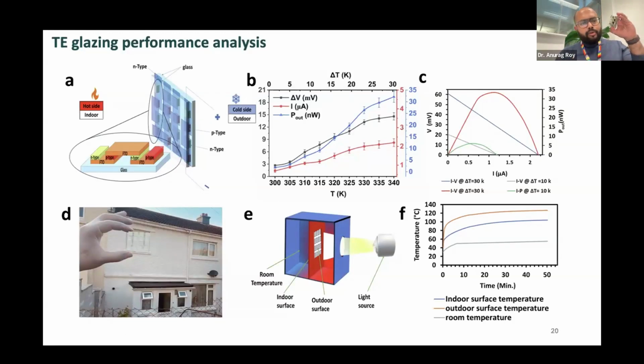So this is our thermoelectric nano generator. One single unit can produce 3 to 5 nanowatt. In this case, this is 4, so we can generate 12 nanowatt of power out of it. This is an example of a building where we used it in the windows, as you can see here. So that can generate the power output, the voltage and the current, as you can see in the picture, as we increase the temperature. And then we apply this.